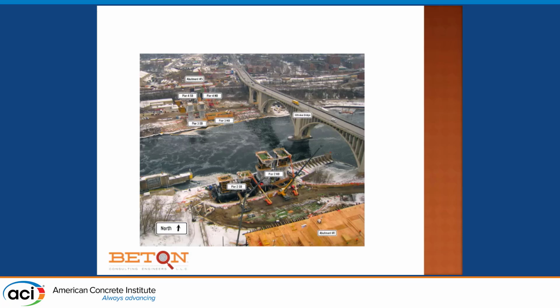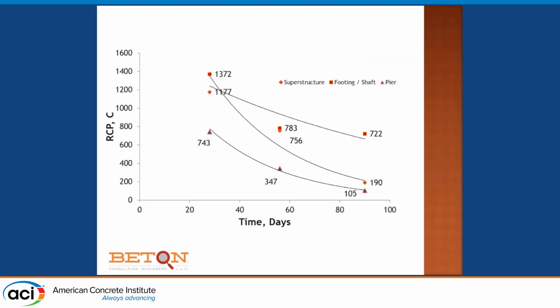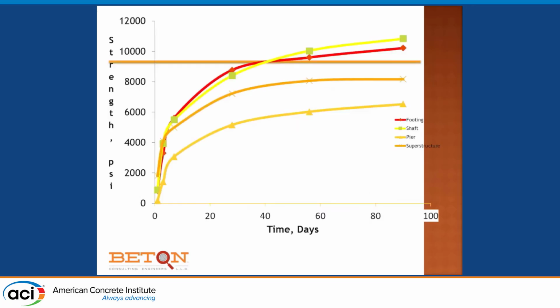We've also done this on a number of bridges. This is the I-35W structure under construction in Minneapolis. It has a little bit of silica fume in some of the mixes, but this is looking at rapid chloride permeability over time. And this is why with things like silica fume in conjunction with slags and fly ash, you're better to look at 90 days. The results are very low, and if we hadn't been tracking the resistivity, we probably would have thought that they were unreasonable. Strengths are always pretty good.